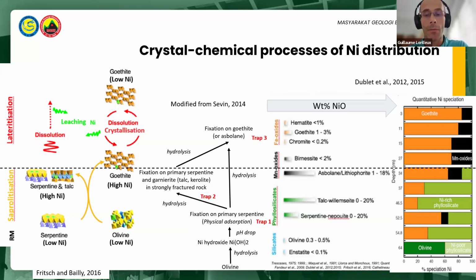Garnierite is a mixture of 3 minerals, serpentine, talc, and smectite, which all vary in composition between magnesium and nickeliferous end members. Garnierite generally forms when early serpentine and iron hydroxide are saturated in nickel and precipitates as coatings, boxworks, and vein infills following shears, joints, and grain boundaries.